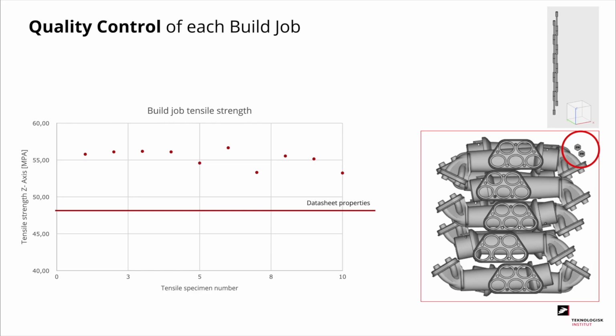Then we bring the tensile bars over for tensile testing, where we test it and enter the results. As we can see here at the red line that we have the default value from the data sheets, in this case from EOS on PA12. And in this case, we can see that all of the test results are well above. This means that we can constantly track how our build job is performing, and if, for instance, there are any layer defects, then it would appear on the graph. This is a really good tool when we run mass production with SLS.